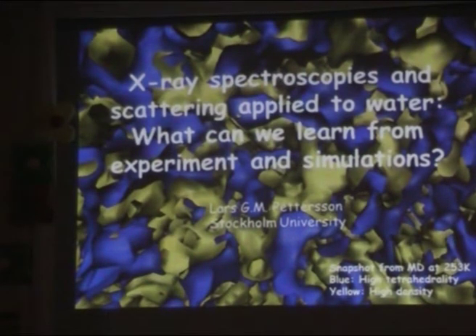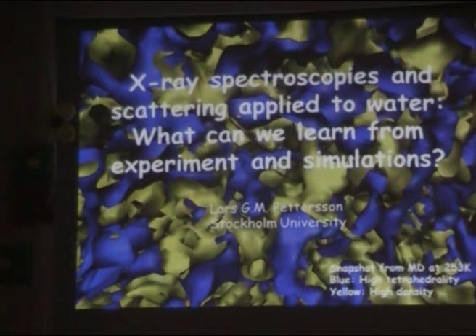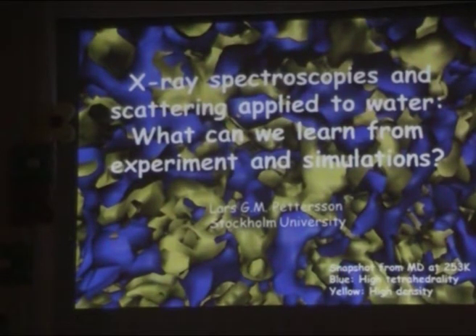Now, what I have here on the screen is a result from a molecular dynamics simulation of water. It's a very supercooled condition, 253 Kelvin. What we have done is we've characterized molecules as being either very tetrahedral, where we use a Q parameter to characterize tetrahedrality, those regions we color in blue. Now, in yellow, we have high-density-like structures. And as we can see here, these two properties are anti-correlated. When we talk about this, we usually call it Swedish water, because those are the colors of the Swedish flag. I guess it could be Ukrainian water as well.